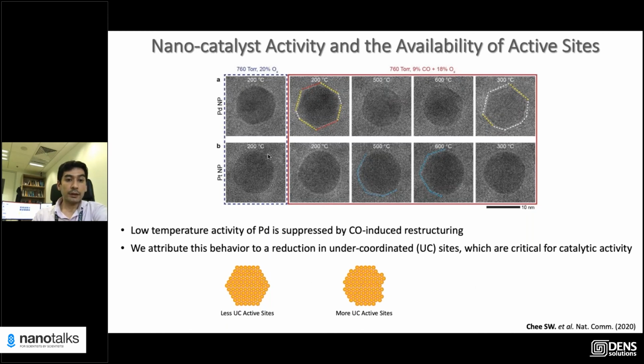And now you can see what's going on. For example, in the case of palladium, when you have a very faceted nanoparticle, you know that your nanoparticle is not active, and you can tie it to the number of uncoordinated sites. But when a nanoparticle becomes active, or rounded, the uncoordinated sites, which usually sit at the corners, become numerous. Once your particle becomes rounded and active, you have a lot of uncoordinated sites, and that's why your activity just jumps up.